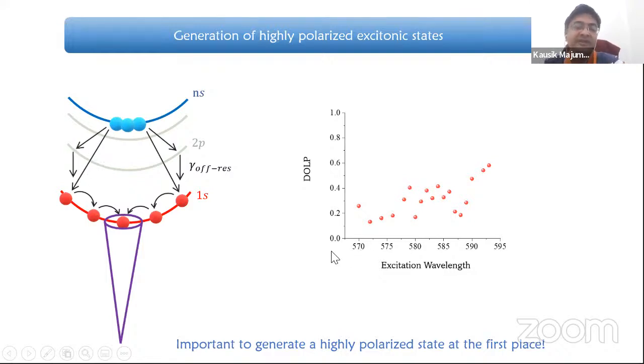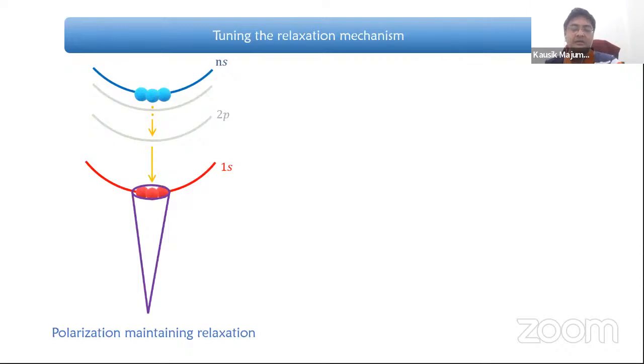So it's very important that we excite as close as possible to this 1s state. And typically in literature, people try to follow that. Otherwise, it's very difficult to do this kind of experiment. But there are a couple of other ways of generating these high-energy states, and this is something we'll use in this talk. The first one is, let's say you excite in a particular state, say a 2s state. Then it's possible to have a transition from 2s to 2p and 2p to 1s directly without phonons. Because of this resonance, it can be a very fast and efficient transfer.